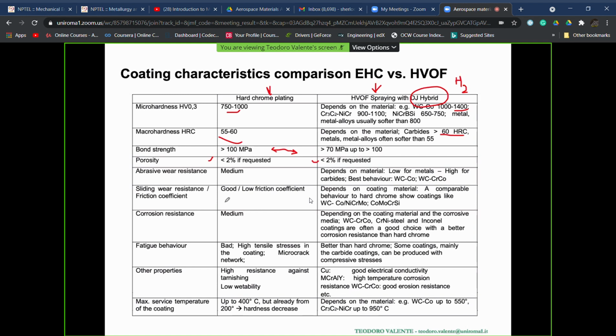And the one which is going to make the difference, and this was one of the elements for which the powder composition has been selected, is the corrosion resistance properties. In terms of fatigue behavior, we can expect better properties from the HVOF with respect to the hard chromium replacement. Well, that's other information. Let's go on.